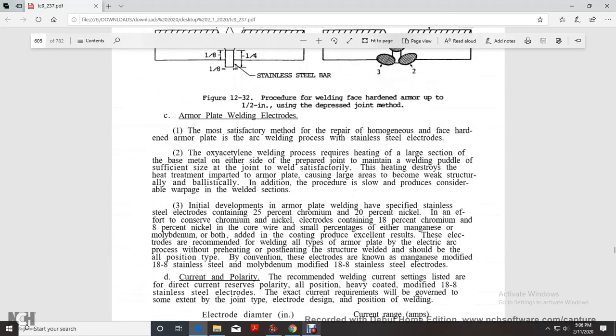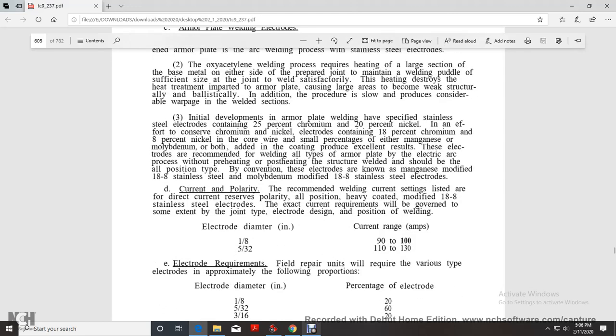Armor plate welding electrodes. The most satisfactory method of repairing homogeneous and face hardened armor plate is the arc welding process with stainless steel electrodes. The oxyacetylene welding process requires heating a large section of the base metal on either side of the joint preparation to maintain the welding pool. This heating destroys the heat treatment of the armor plate, causing the large area to become weak structurally and ballistically. The procedure is also slow and considerably warps the welded section.